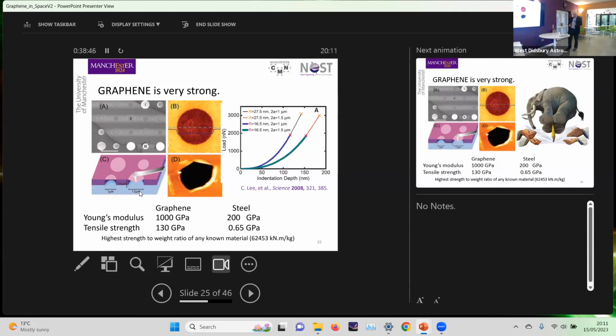And it turns out the experiment was really difficult to do, because the tip on our little silicon cantilevers kept breaking before it went through the surface. So we had to get stronger cantilever styluses in order to break through the surface. And then it turned out, when we looked at the results, that in fact it's got a tensile strength 200 times that of steel. So its tensile strength is huge. Also of importance is the fact that it's very light. So its strength to weight ratio is the highest of any known material. It's huge, absolutely huge.